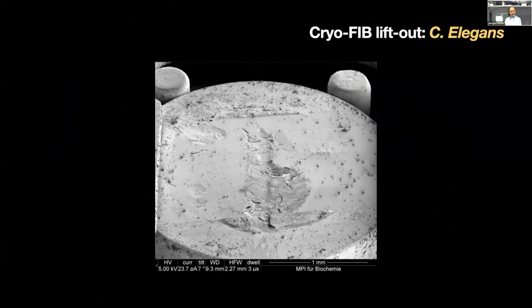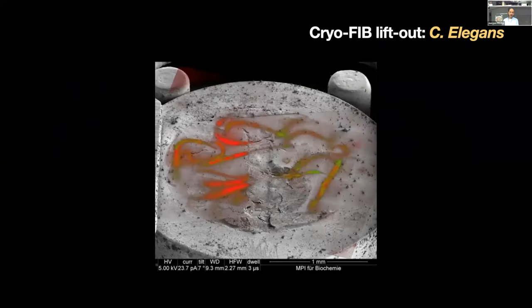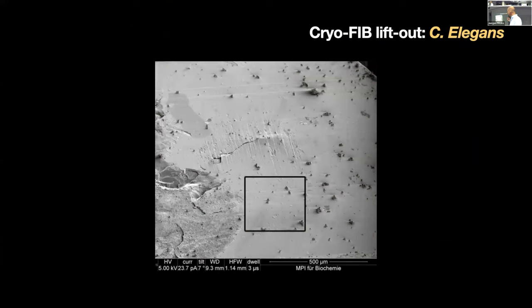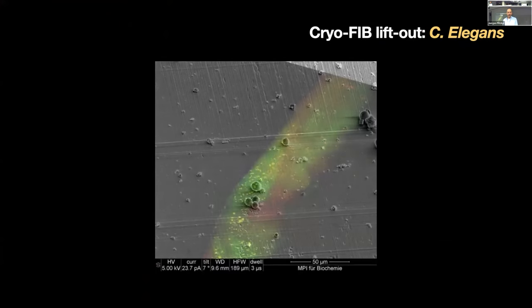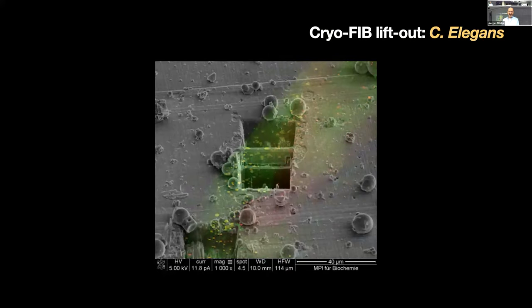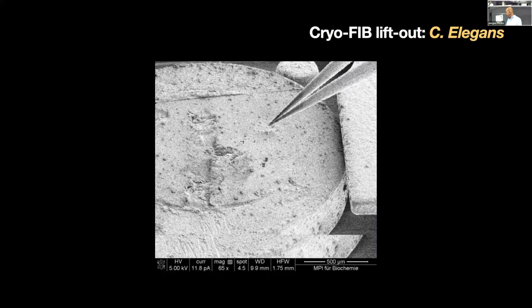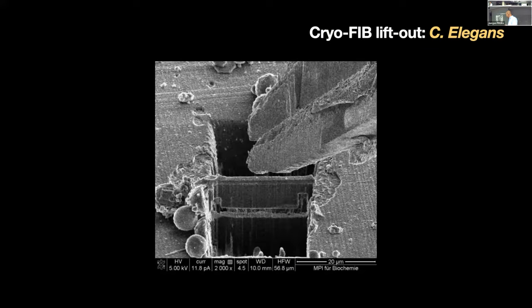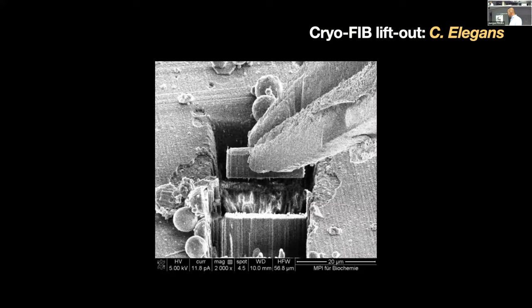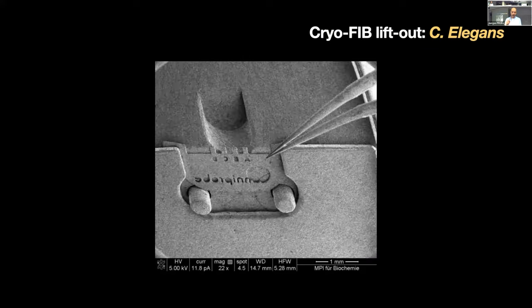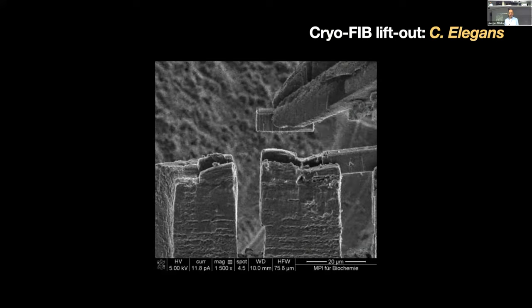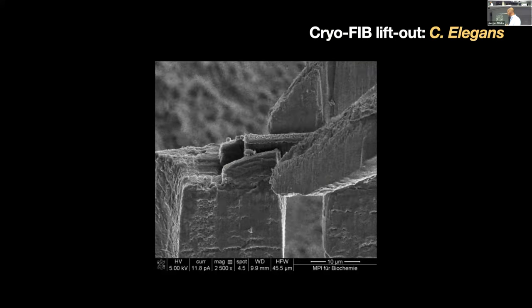And then you have that big planchet and you have to locate that C. elegans organism. And of course, everybody can see the C. elegans in that image. No. But if you forward that movie, you can clearly see in the fluorescence microscopy image where C. elegans is. And then you can dig in these areas and lift out a very, very small, tiny volume out of that planchet, of that high pressure frozen device.